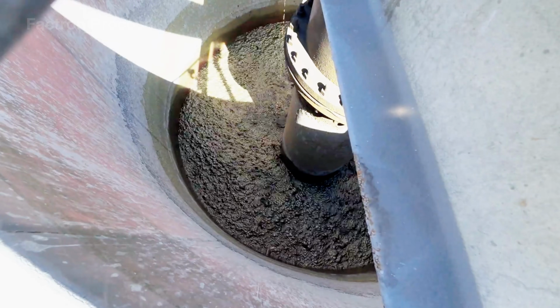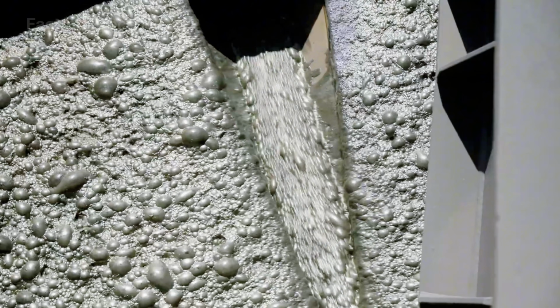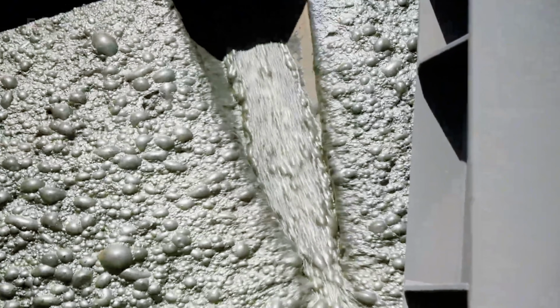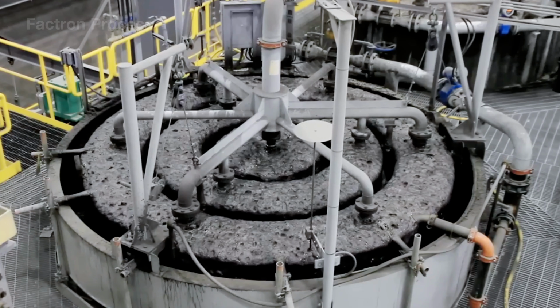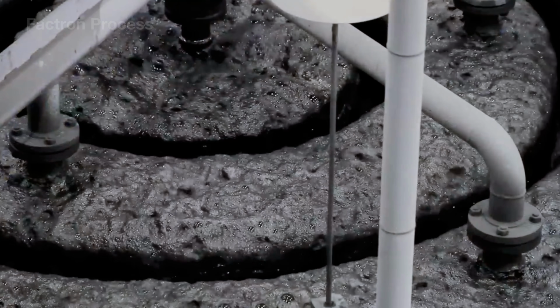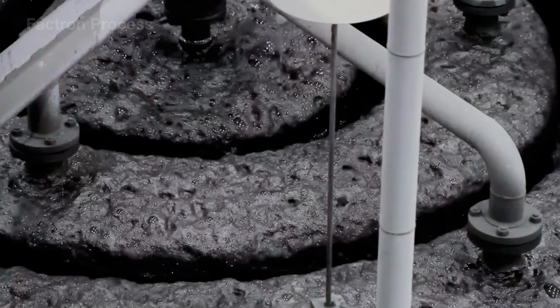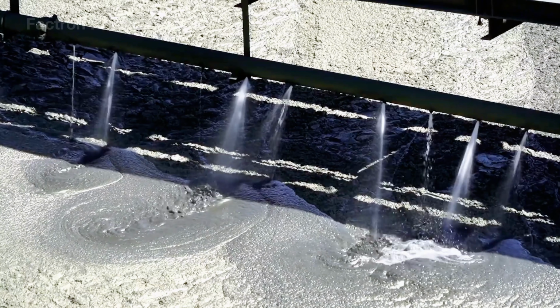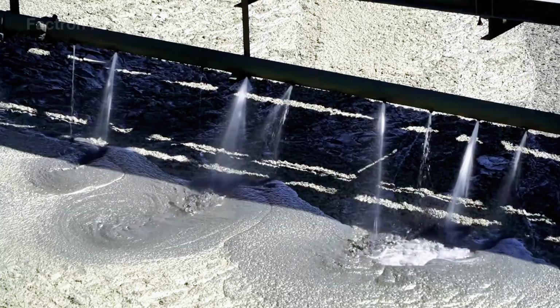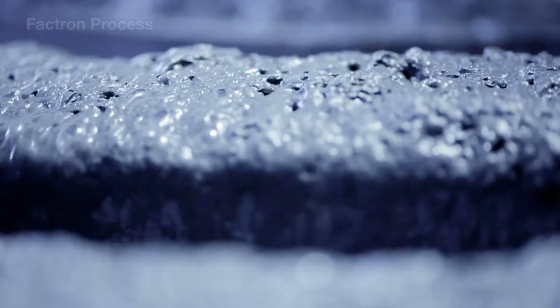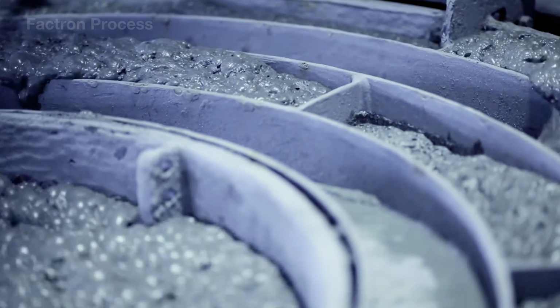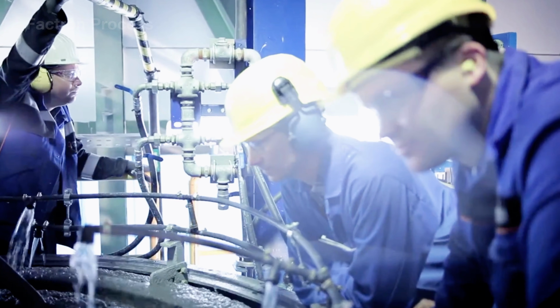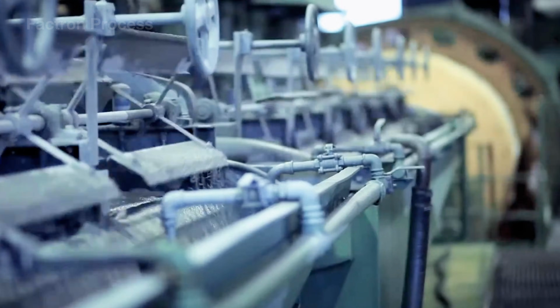As air is continuously injected from the bottom of the cells, millions of tiny bubbles quickly form. The copper mineral particles coated with reagent attach themselves to these bubbles and gradually rise to the surface, while most of the waste rock remains below. Through this mechanism, ore containing only around 1% copper can be upgraded into copper concentrate containing approximately 25% to 35% copper, making it suitable for the smelting stage.